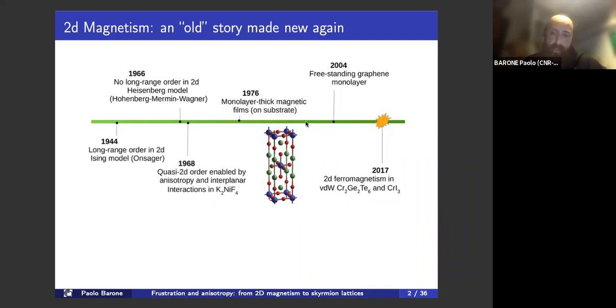The prototypical system is shown here as this 3-dimensional structure, where basically long-range magnetic order is established only along the layers containing the magnetic nickel ions. And this started a field of, let's say, 2D magnetism, so quasi-2-dimensional magnetism in bulk systems, that has been very active, especially during the 90s, because of its close connection with the parent compounds of high-Tc superconducting cuprates.